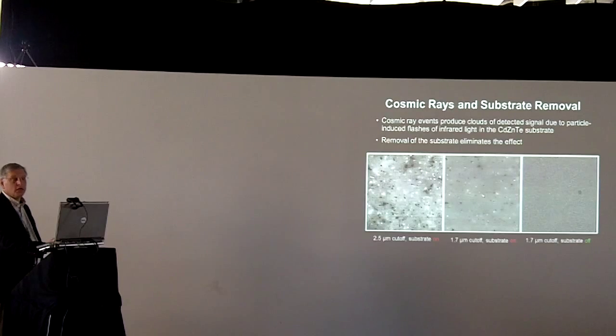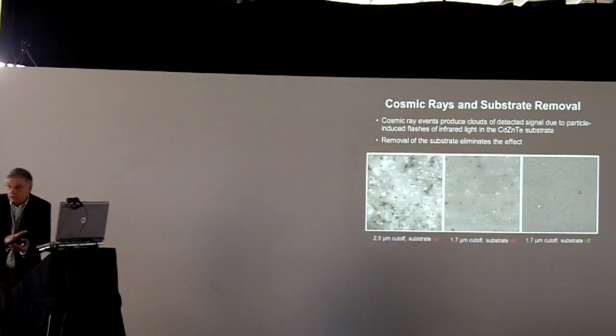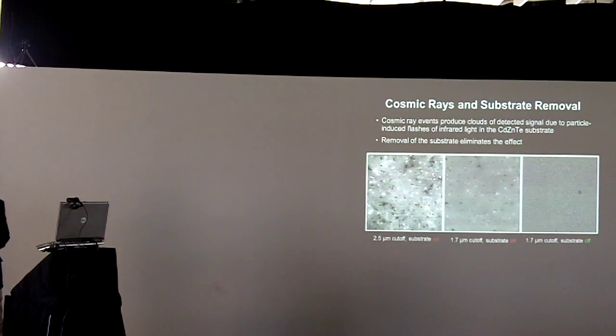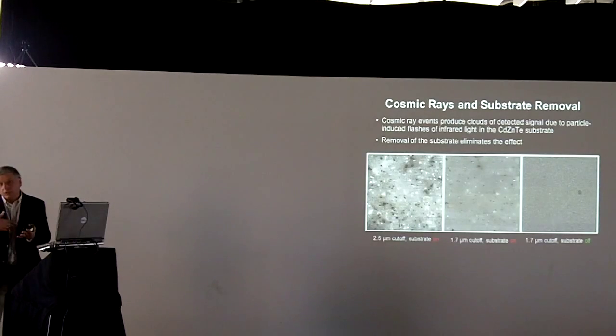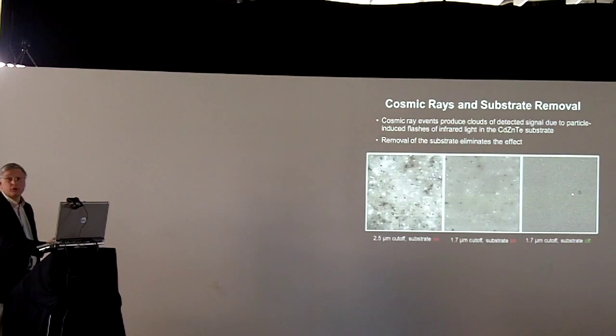detected in the substrate. You remove that substrate by polishing it, if you've ever polished a mirror, or actually milling it, like with a milling machine, a very special milling machine. And then at the end you do a selective chemical etch to remove the CdZnTe, and then you process the backside. And when you have substrate removed material, now you don't have a cosmic ray detector sitting right in front